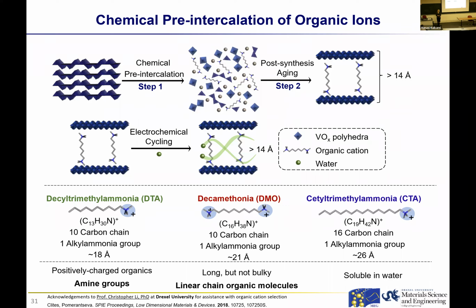So now I hope everyone remembers, the best results so far we have achieved with the magnesium pre-intercalated bilayered vanadium oxide that had the largest interlayer region. So naturally, we wanted to expand the interlayer spacing of the bilayered vanadium oxide further. In order to do that, we selected linear organic molecules of different lengths with amine groups, which introduce the positive charge needed for these organic molecules to be incorporated into the interlayer region during material synthesis.